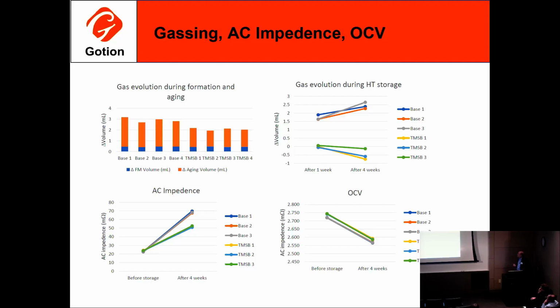So here's your baseline electrolyte for gas evolution during high temperature storage, and with our additives, we're basically somewhere near zero as far as the amount of gas being evolved, the quantity. So we made good progress there, and over in this, currently, obviously, impedance growth is a bad thing from a long-term calendar life, and so how do you improve that? So we made some improvements there as well.